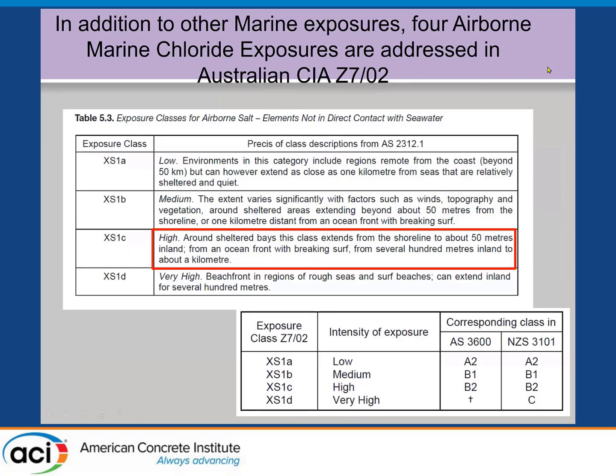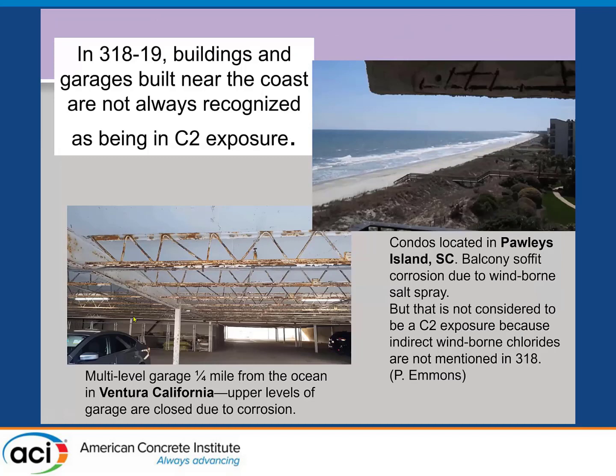And just on this airborne marine exposure, because it's a deficiency, I think, in 318. The Australian code talks about chloride exposures for sea spray that can go in beyond 50 kilometers, so it's moderate there. But even at their high exposure, it could be up to a kilometer, almost more than half a mile in from the shore. It can be a very high exposure just from airborne spray of salt water. And so it's something that's not addressed in 318 at all, and this has led to problems. Structures built near the coast, like these condos in South Carolina, they're well back from the shore. They're not directly exposed to salt water, but they're exposed to salt spray, and you may be able to see this. The soffits are all corroded after a short period of time. And that's a big problem with a lot of buildings along the shore in Florida and elsewhere.